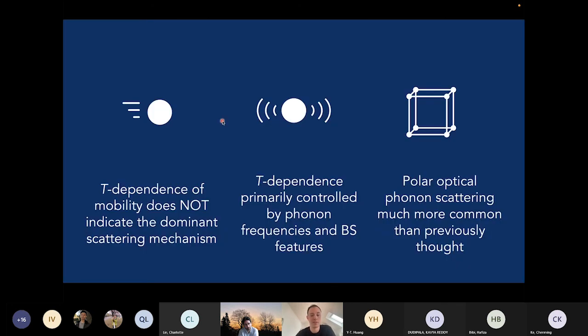So that's my talk. I've introduced a new approach for calculating scattering in semiconductors and calculating transport properties. And then I've used that to understand the temperature dependence of carrier mobility. I really hope I've convinced you that the temperature dependence of mobility doesn't indicate anything about the dominant scattering mechanism. In fact, the temperature dependence is almost entirely controlled by the phonon frequencies and, to a lesser extent, the band structure features. And based on these results, it seems like polar optical phonon scattering is much more common in materials than we've previously thought.